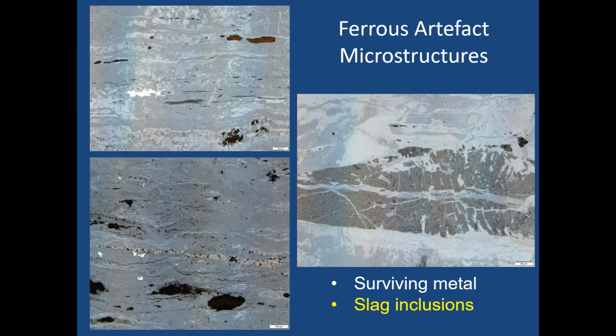It's the most studied alloy in engineering terms in the world, so we have a very good idea of what it looks like under the microscope, and he can relate these microstructures to different levels of steel, mild and medium steel, which we're finding at the site. And the evidence suggests that these artefacts are occasionally of steel, but they're very heterogeneous. They probably weren't intentionally made of steel at this point. But because most of the material is very heavily corroded, he's forced to rely not on the analyses of the small remaining islands of metal, but on these smaller inclusions of slag which are found throughout the samples.